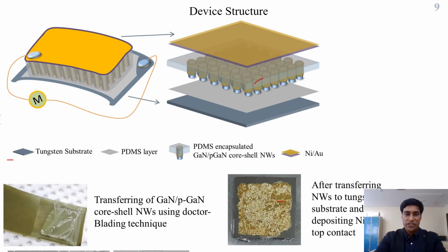And this is the device structure. First we grew the gallium nitride nanowires on a gallium nitride thin film. Then we encapsulated the nanowires inside PDMS using the spin coating technique, and then we transferred the PDMS-encapsulated nanowires using the doctor blading technique. After that, we transferred this nanowire PDMS matrix onto the tungsten substrate, and then we deposited the top contact, Ni/Au.